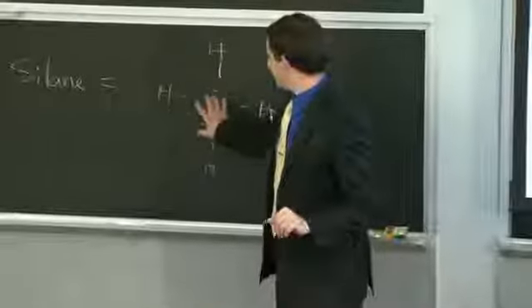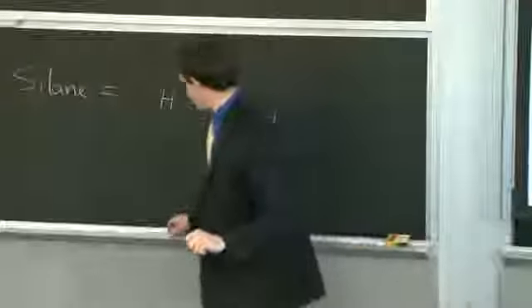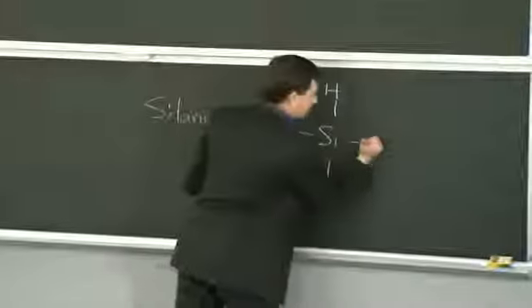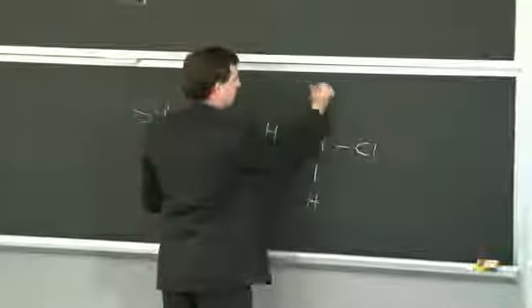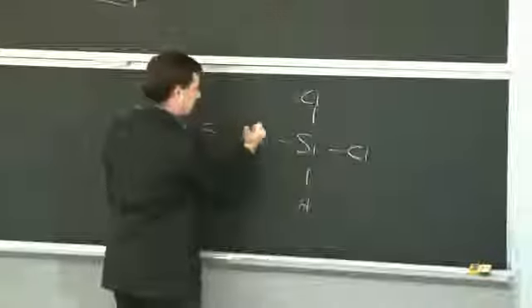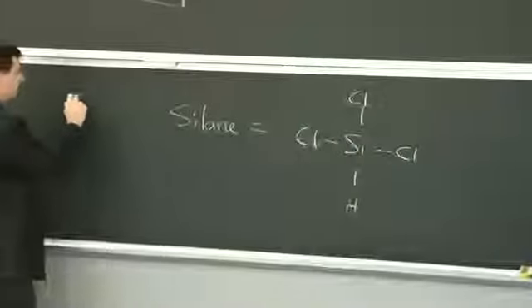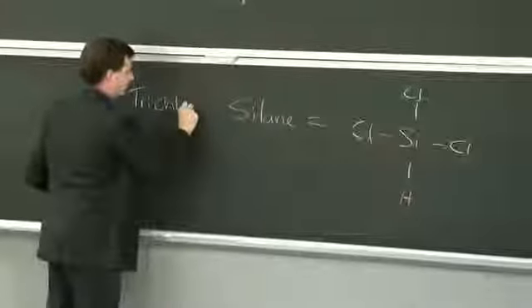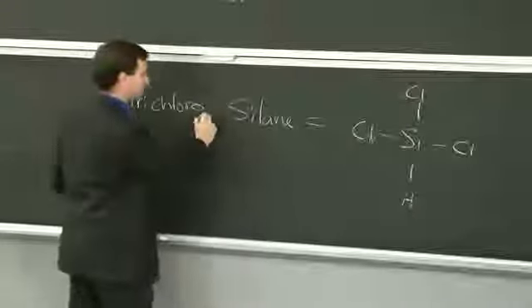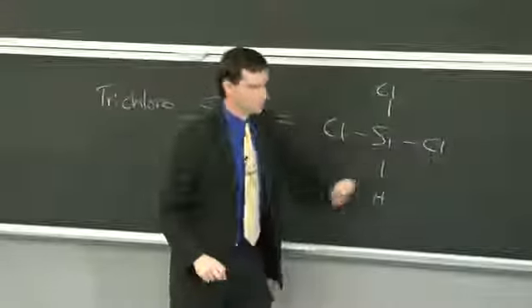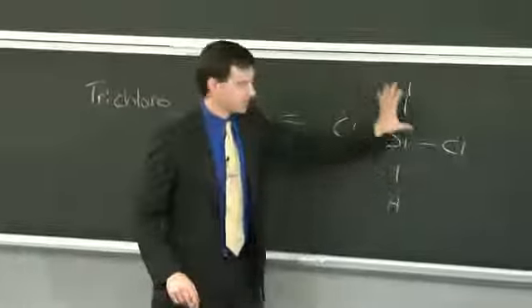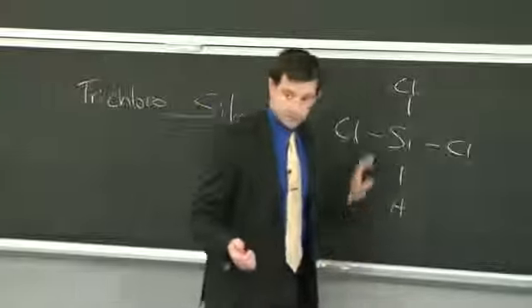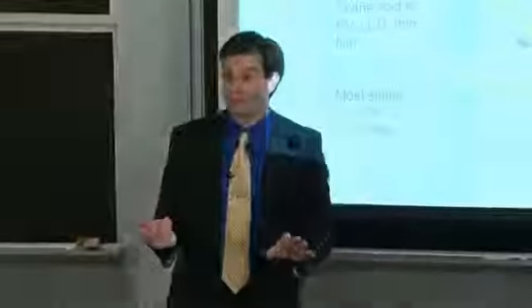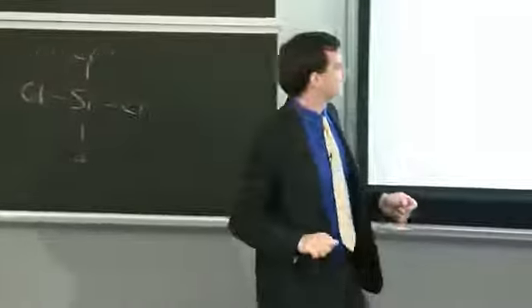So we have this gas right here, extremely pyrophoric. There are variants thereof. You can replace some of the hydrogens with chlorine, like this, and now you have trichlorosilane. It's all one word. So trichlorosilane, I've just replaced 3 of my hydrogens with chlorine, and now I have a different molecule, still silicon bearing, still very reactive, but now reactive at different temperatures. And I can modify my process by substituting out some of the hydrogens for chlorines.